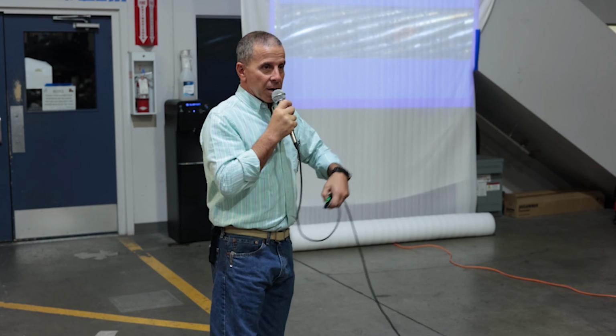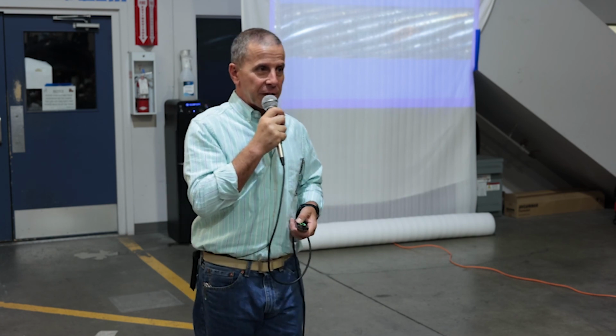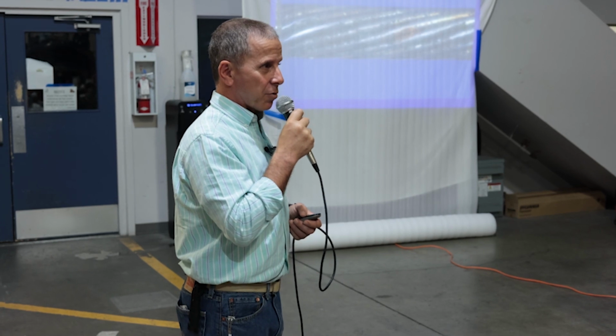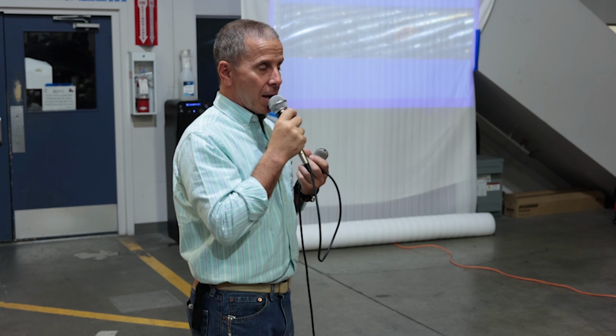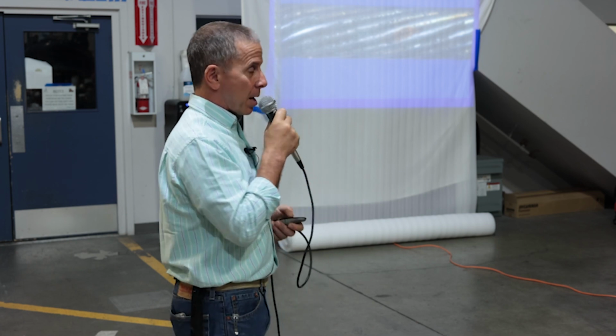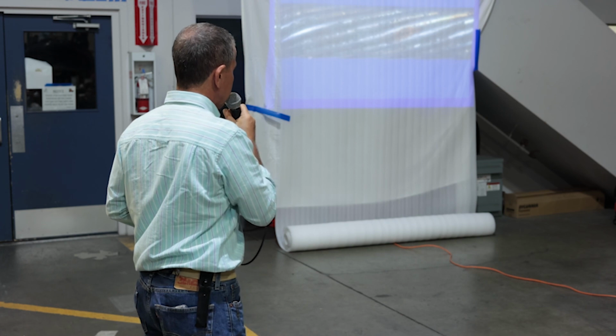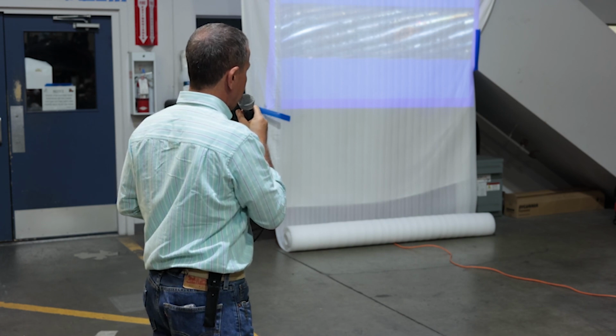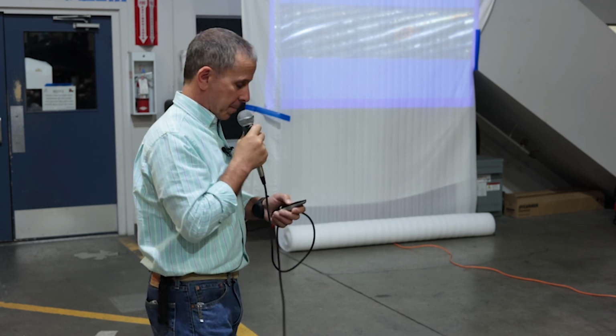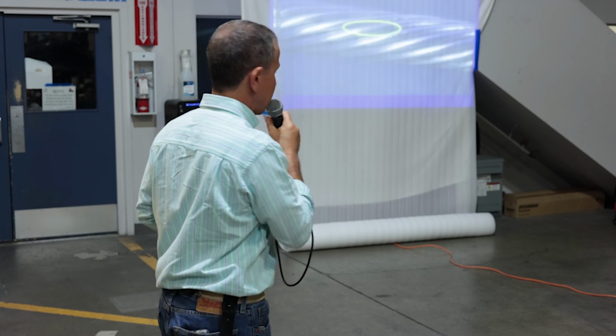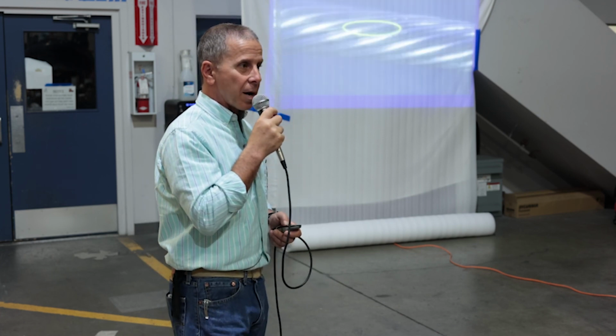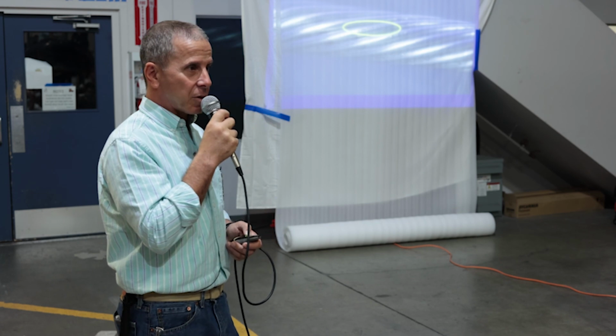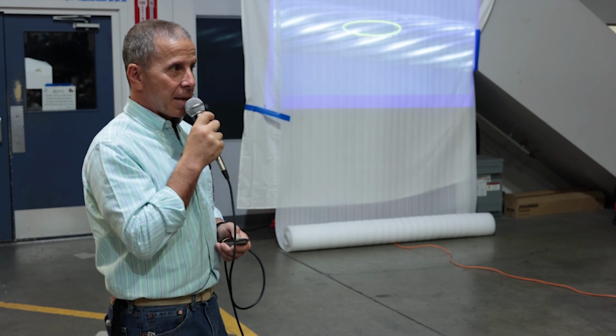Stainless steel wire, even if it becomes dirty, interestingly, can be subject to this crevice corrosion scenario. The dirt can actually hold water and trap water between the strands of the wire. So in this case, there's a little tiny brown spot there that caught my attention. And when I clean that wire, I can see that that strand of wire was beginning to crevice corrode. It's got pitting in it.